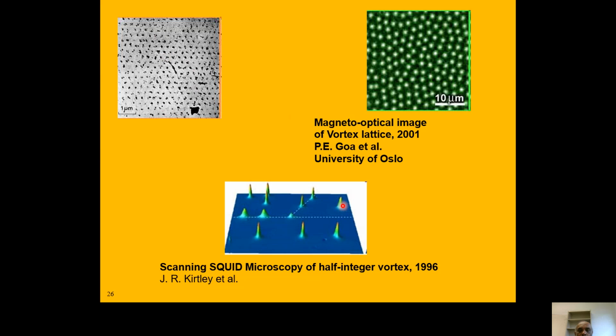When you do magneto-optical imaging, you can see this nicely, because with magneto-optical imaging you can observe the magnetic field. These dots are the vortices, because through the vortices you have magnetic field penetrating, which you can see, but everywhere else is superconducting with no penetration of magnetic field. These bright white spots are the vortices. Even here, though it's not a very good image, you can see the areas where these vortices are showing up, which are the places you have magnetic flux coming through.